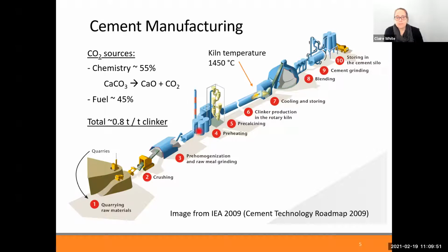This all gets processed and fed into a very high temperature kiln. There's a lot of solid state reactions that occur in this kiln that produces a material known as clinker, which then gets mixed with gypsum, which is a calcium sulfate phase, and that's essentially the cement powder that we use. And so what's going on in the kiln here is really where the CO2 emissions come from. Because we're digging out limestone, which is calcium carbonate, once you heat it past about 800 degrees Celsius, it decomposes into calcium oxide and carbon dioxide. And the carbon dioxide at the moment is going into the atmosphere.